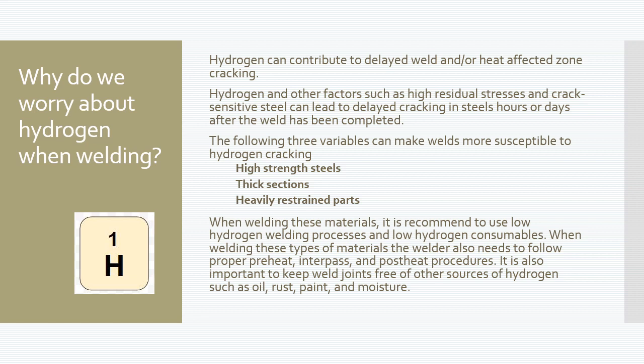But one of the things we want to do is not introduce that hydrogen into the weld metal to start with. So that's why we talk about using low hydrogen consumables, something like a 7018. 6010 is not a low hydrogen material because it's got organic matter in it. It's made out of wood chips and paper and pulp type materials.